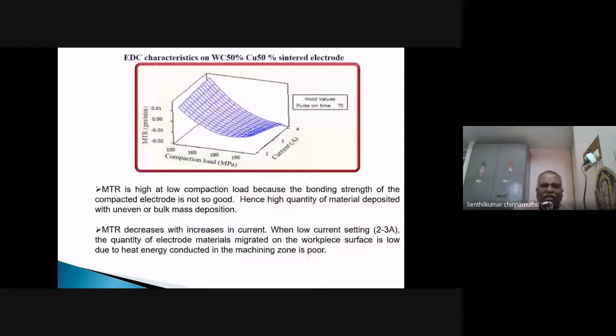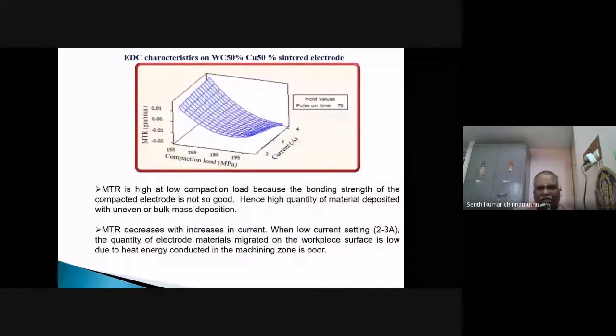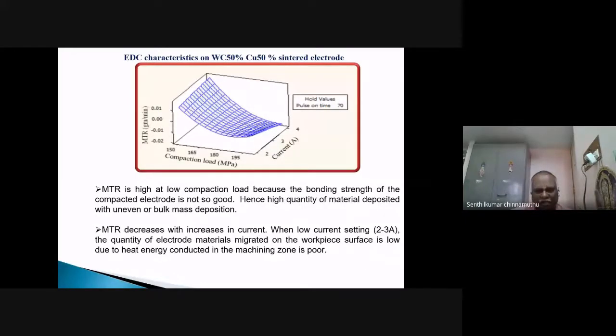And the EDC characteristics on 50% tungsten carbide copper sintered electrode, the effect of compaction load and current on metal transfer rate. At lower compaction load, similar to semi-sintered, the metal transfer rate is higher, but at higher compaction load, the metal transfer rate is negative. That is called metal removal. Conversely, instead of metal transfer, at higher compaction load, material removal takes place because it resembles a solid metal. Similarly, in the case of current, at lower current material deposition takes place, but at higher current, material removal takes place.